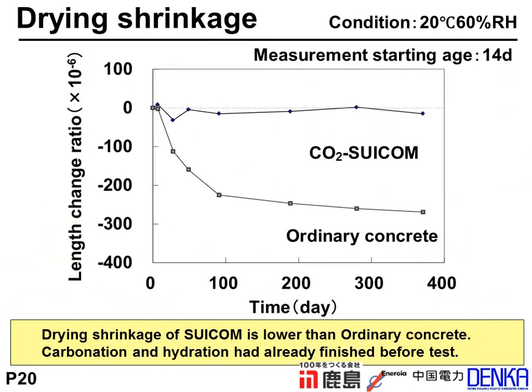This figure is the result of drying shrinkage of the concrete. The measurement condition is 20 degrees Celsius and 60% relative humidity. And we cured the specimen for 14 days. The drying shrinkage of CO2-SUICOM is very low, lower than ordinary concrete, and it kept a constant value. We assume that the carbonation and hydration had already finished before the test. So the CO2-SUICOM kept a low drying shrinkage.